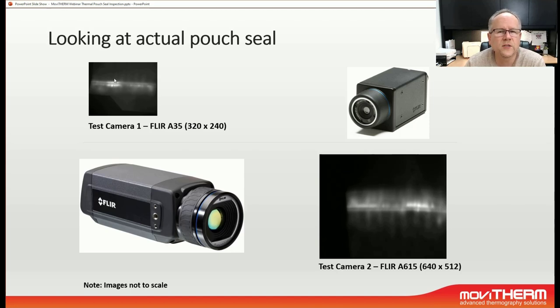We also see the bright spot here, and that is a heat concentration in the seal. And this could have several reasons. One thing, it could be a concentration of adhesive, it could be a misalignment on the sealing fixture, or it could be also a folded over piece of material there that created more friction. All of those things are possible because the sealing mechanism here is really ultrasound. So all of this could be a possible cause for this heat concentration here.